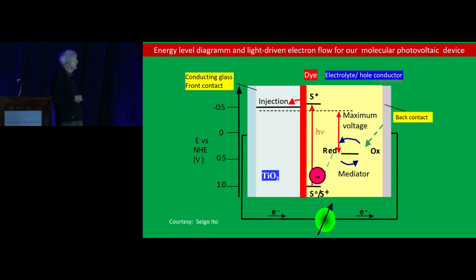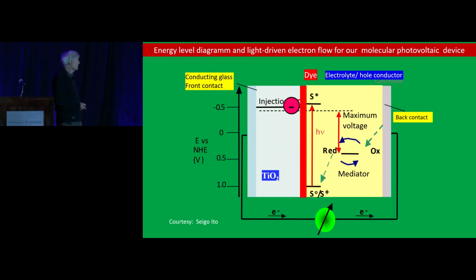One way to mimic the primary reaction in photosynthesis is to use a sensitized semiconductor concept. So we have a large bandgap semiconductor like TiO2, the white paint, and use the conduction band level of this semiconductor to act as an electron acceptor. On the surface, we have an adsorbed sensitizer molecule, a self-assembled monolayer, which will do the light absorption. When light is hitting the sensitizer, the machine gets put in motion, electrons are injected, they do their work outside in the circuit, and then we get the electron back through a shuttle that has to bring the charges back to the sensitizer.